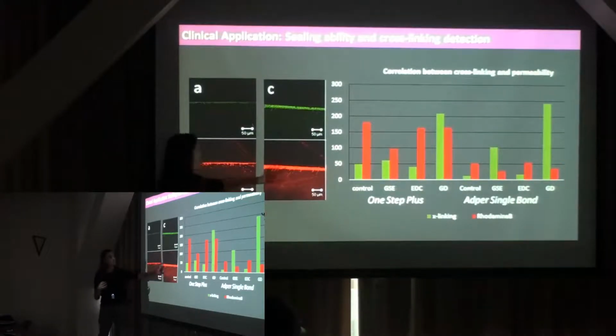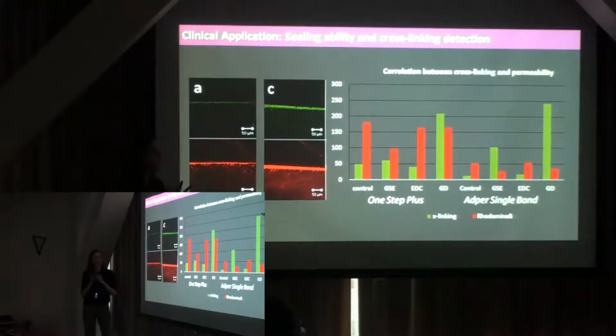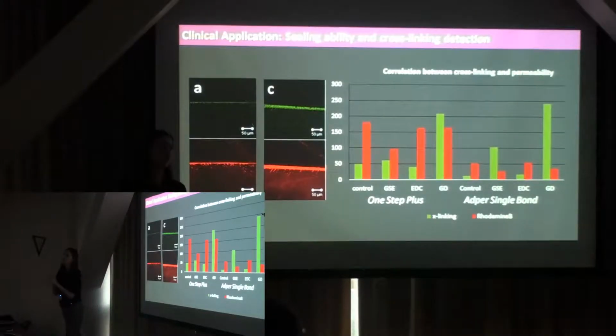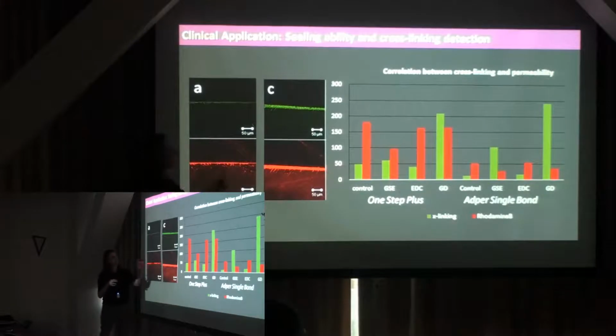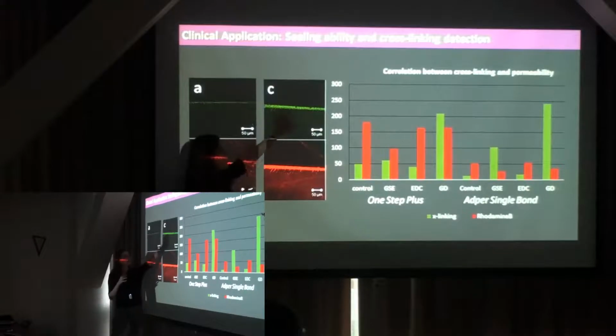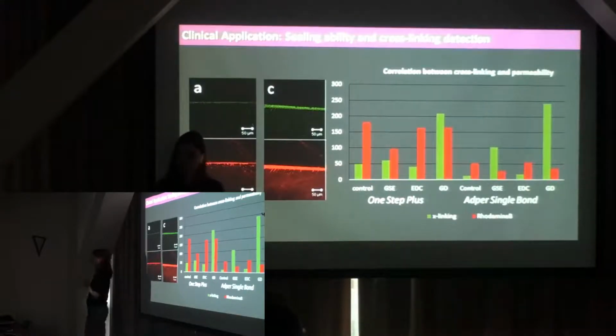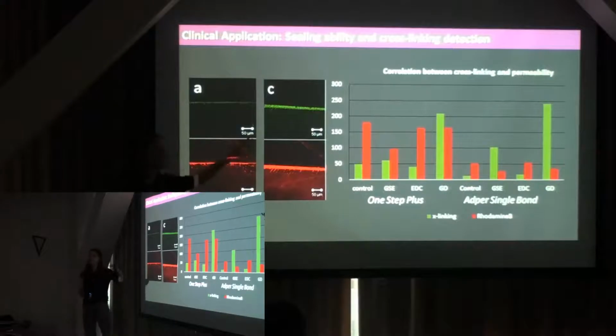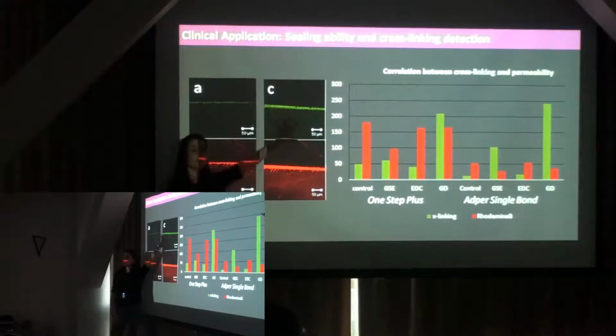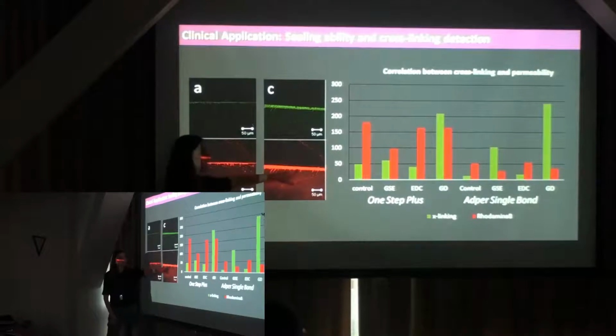So what we do is that we go into the confocal laser microscopy. We use rhodamine as a fluorescent dye, and we seal everything around except that interface. We leave it there for about an hour, and we take it to the confocal immediately. And most of the non-reducible collagen crosslinks are fluorescent, so you can pick them up too. So now we use this as a method to characterize the degradation over a period of time and correlate the degradation of this collagen with the porosities over that interface.